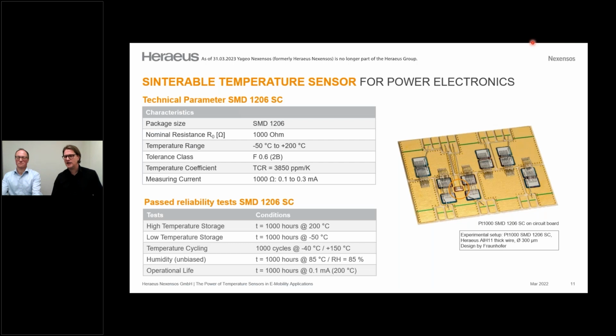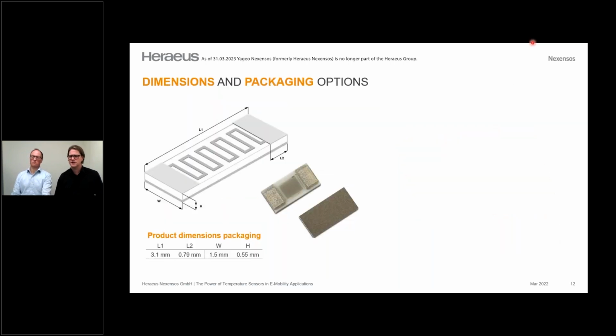And a really harsh test is an unbiased humidity test. We made a 85 degrees test with an 85% humidity, and typically a lot of components will fail under that test, but our sensor passed also that test. And in the end, we had an operational life test, 1000 hours, really biased with 0.1 milliamperes and at 200 degrees, and also this test was passed. That means this is our understanding of quality.